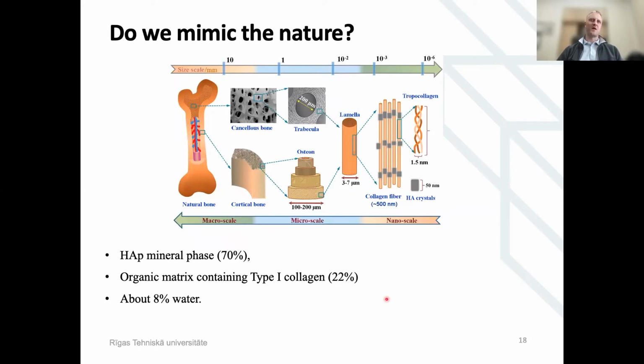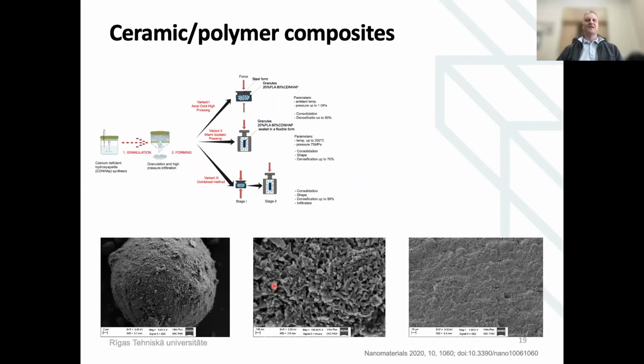Not yet. From one part, we can mimic that we have nanoparticles in our composite, but we still lack the organic phase. So no organic phase at this point. And then together with our partners from Poland, from the Institute of High Pressure Physics, we developed one very nice technique. In this case, it was nanohydroxyapatite. We found a way to make nice granules out of that. And at the same time, we introduced in this composition 20% of organic phase, polylactic acid, which is a biodegradable polymer. So, trying to mimic at least from the combination of inorganic to organic phase, the composition of bone.